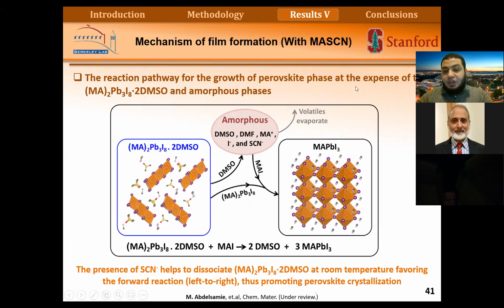And from this, we could also understand the reaction pathway. So this is the blue material. It has this composition. This material reacts with the amorphous material surrounding it, which has different components. It has MAI, and this reaction happens, and then we form the final product, which is the perovskite material. And the additive here helps to dissociate this. So this reaction can go both ways. The perovskite can dissociate into the intermediate in the presence of solvent. But if we have the additive, we have found that it destabilizes this compound. It reacts with this compound and makes it unstable. So this dissociates, and after dissociation, these molecules diffuse and also join some amorphous material, and both of them contribute to the growth of the crystalline phase. And the DMSO, being a solvent, goes to the amorphous material, and from the amorphous material it goes outside the film, so it evaporates eventually with the drying. The presence of additives here was very important, as it helps to dissociate the intermediate phases and form the final crystalline phase.